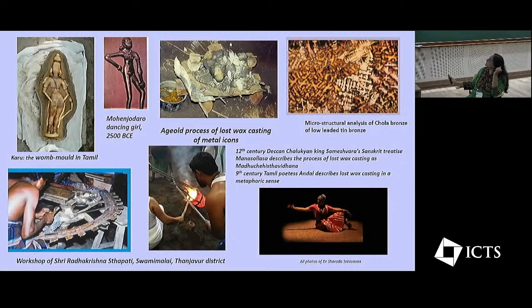And then once the mold has been made, the whole idea of the lost wax process is that when you heat the mold, the wax gets expelled. And inside the mold, you get a hollow exactly in the shape of the image to be cast. And here you see the wax has been expelled from this mold. And then the metal is heated, and then the molten metal is poured inside the mold so that it takes the shape of this hollow which has been left from the wax being melted out. And then that is broken open, and final finishing and so on is done in the casting to yield the final finished image. And now I had also done microstructural analysis.